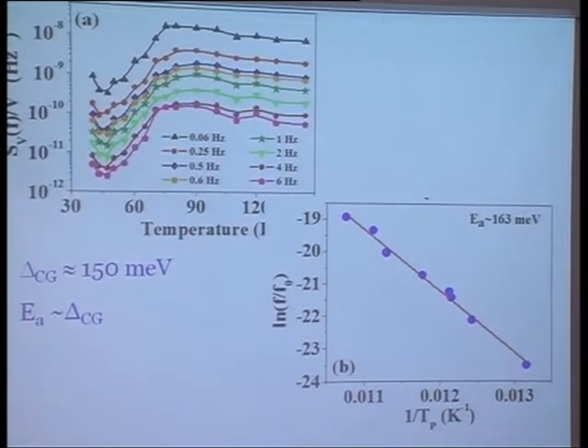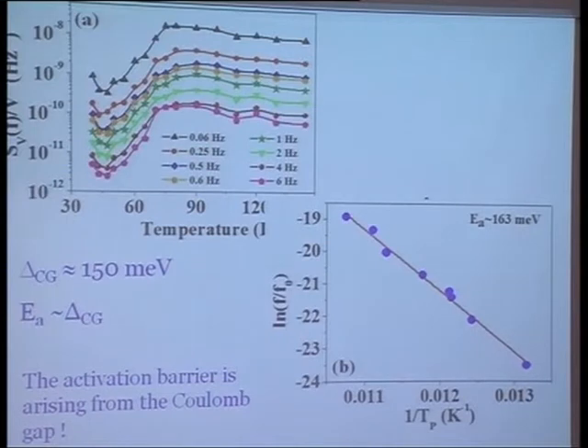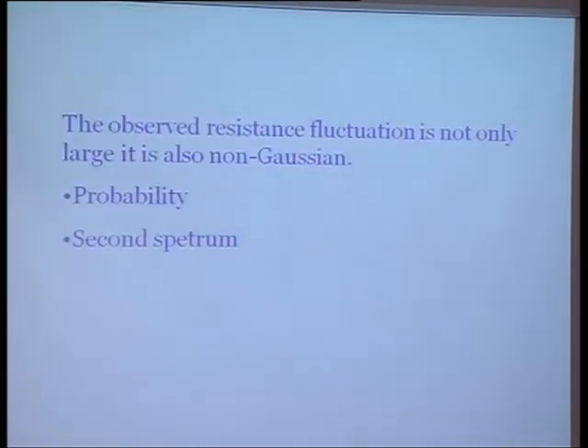And if you remember, they're very different experiments. This came from heat capacity, and this came from your noise freezing. So their closeness is, I think, very gratifying to see. So the important conclusion that you could draw is that there is indeed an activation barrier to the fluctuation, and it is coming from the Coulomb gap.